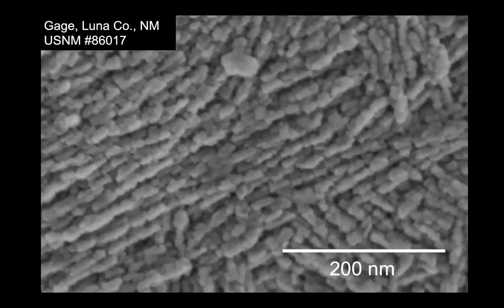And this reveals to us that the goethite is growing by oriented aggregation as well. We see these linear fibers on the surface, but they're segmented. I think of them as kind of like sausages that are all attached to each other. And we weren't too surprised because Penn, who's at the University of Minnesota and has published a lot of papers in oriented aggregation, has done much of her work in the goethite system. And so she's shown really conclusively that goethite often grows through this oriented aggregation process.